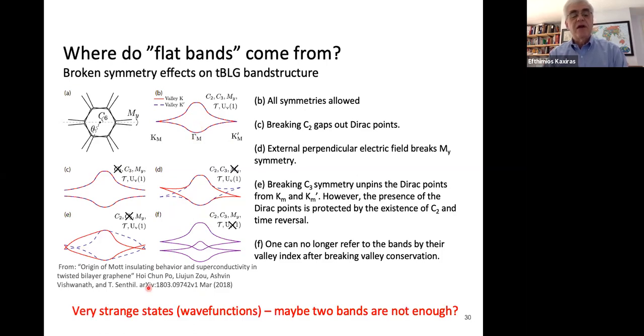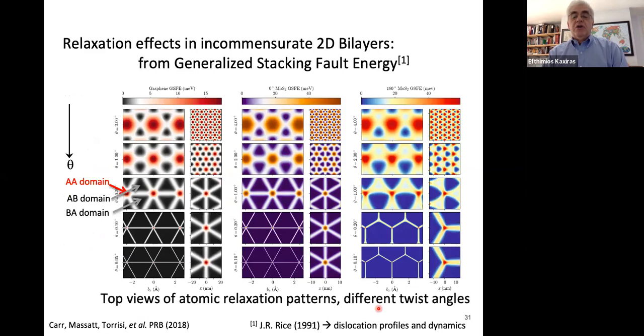But it turns out that if you take that a step further, you find very strange wave functions for these states, suggesting that maybe two bands alone are not enough to describe the system. So in order to really nail down the question, you have to take into consideration the atomic structure. So here are the results of our atomic structure relaxation calculation. So we have the tools to do that as well. I don't have time to explain the details, but let's just look at the results.